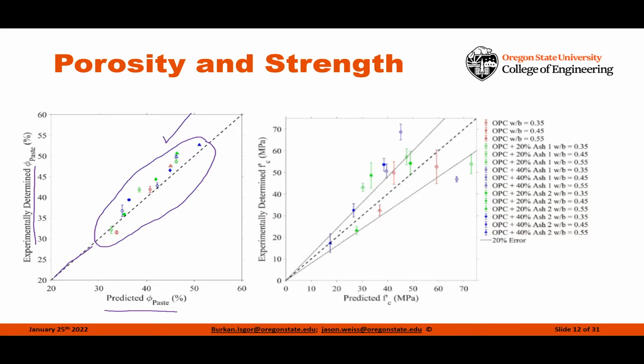Now, if we start to extend that, we can extend it to things like strength. And here we have a simple extension to compressive strength. And what we start to see is the variation gets a little bit wider, but we do have a fairly good correlation between the predicted compressive strength and the experimentally measured compressive strength, starting only with the initial chemistry of the system, the volume of the cements, the volume of the aggregates, and predicting this out.